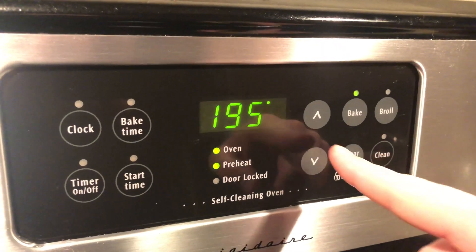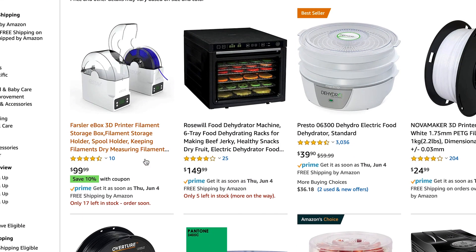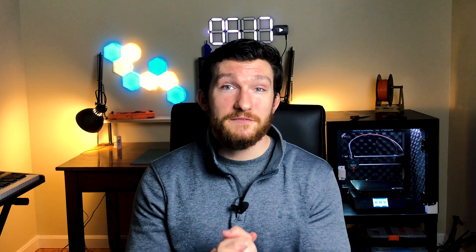If you decide to bake your filament, you'll need to research your filament's glass transition temperature and set the oven just below that. For PLA, which has a glass transition temperature around 60 to 65 degrees Celsius (about 140 degrees Fahrenheit), you'll want to set your oven to about 135 degrees Fahrenheit and bake your filament for 4 to 6 hours. I'll throw a link in the description where you can look up the glass transition temperature for your filament. The downside of this method is that some ovens don't actually go that low. In that case, you might want to look into getting a special filament drying machine or a food dehydrator, which I'll also have linked in the description. But if your goal is to find a cheap solution, at around 20 bucks, this dry box is a great place to start.